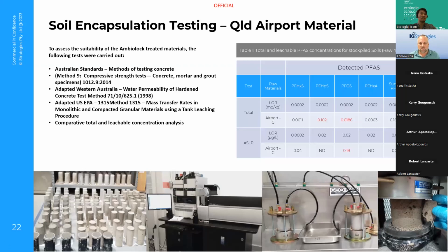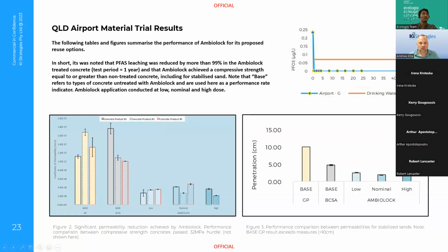So we did some laboratory scale testing to see what could be achieved, creating a large number of monoliths and putting those monoliths through a range of different tests to look at compressive strength, permeability, and the amount of PFAS that was leaching following treatment. Next slide, please, Dwayne. And we were able to achieve significant reductions in permeability.